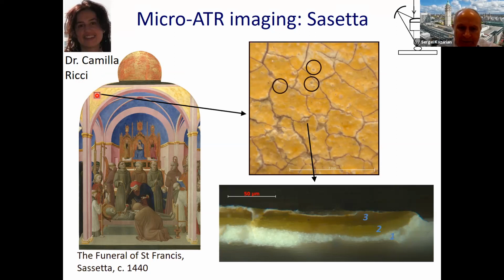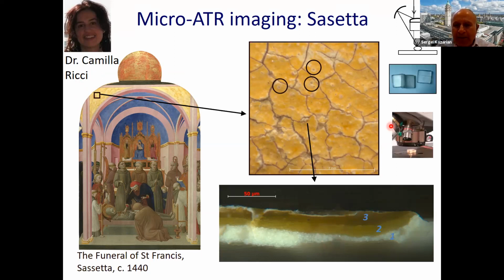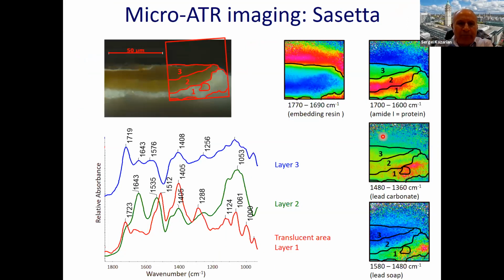So the sample had been extracted from this part of the painting by Sassetta, particularly to analyze these translucent areas or regions in the sample. And you can see by visible microscope, there are different layers. And of course, these microscopic samples have been embedded in epoxy in order to handle them under the microscope. So, and these are really interesting results, because you can see now chemical images based on distribution of spectral bands. And here we have resin, of course. It's not much of interest, but the exciting part came here.